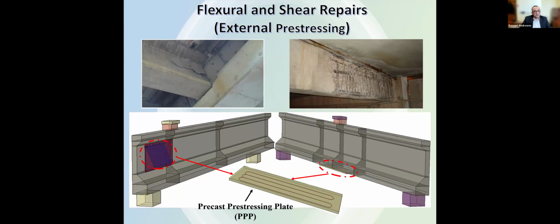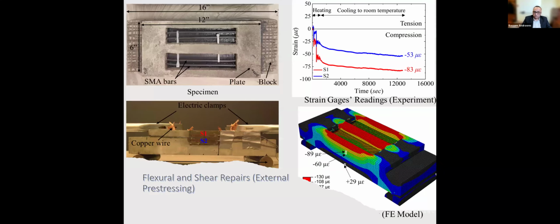So we tried this concept with different variants. This is one of the designs we came up with, which is the voided plate. So here you see 2 voids with the 4 SMA bars exposed. Part of the reason is that we wanted to inspect the bars during the heating process, but also we wanted to make heating easier. And then we mounted it on the block here to see how much of the pre-stress will transfer to that block. By the way, attaching the plate to the block or the girder could be done using epoxy or mechanical anchorage or even a combination of both.